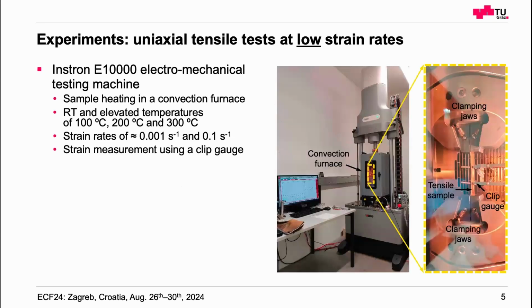Now I show you which experiments we performed. First, we did uniaxial tensile tests at low strain rates. There we used our Instron E10000 electromechanical testing machine. There we have the possibility to use a convection furnace, and it was possible to perform these tests from room temperature up to 300 degrees. And we tested here strain rates at quasi-static and also at a strain rate of 0.1. And the strain was measured by using a clip gauge directly on the sample in the furnace.